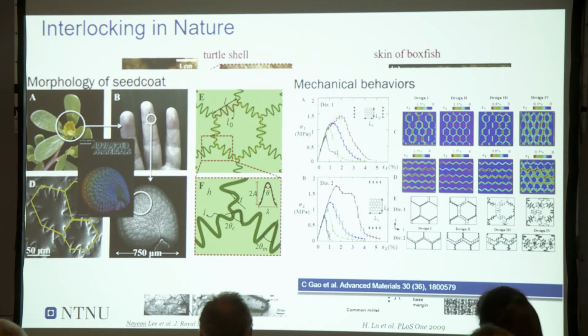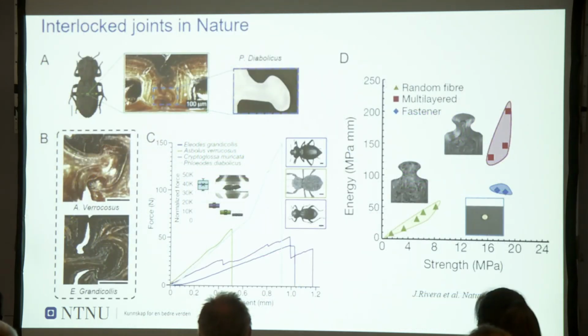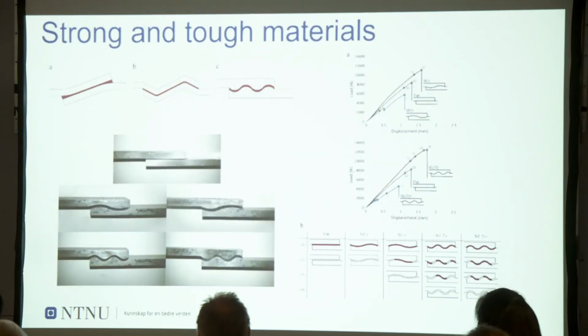This is a recent study from Professor Chao Gao in our group that studied the interlocking mechanism in this kind of seed coat, showing that it's possible to tune the interface with different wavelengths and to obtain different values of ultimate strength and also fracture toughness of the material. But this is another example that we have studied recently with another student, working for example on this kind of structure that is the shell of this animal. Strong and tough materials can allow us to obtain high strength and high toughness. What about fatigue?